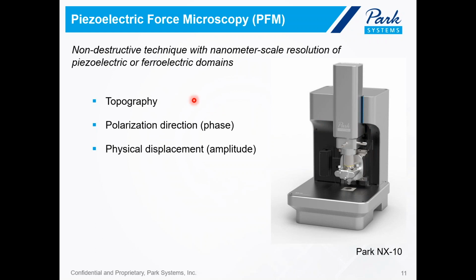So in PFM, we have 3 channels mainly. The topography channel is very self-explanatory. From the topography channel, what we can learn is the features at our surface, the topography, the morphology. And then we have a PFM phase and a PFM amplitude channel. From the PFM phase channel, we can get the polarization direction. And on the other hand, from the PFM amplitude channel, we can get the physical displacement. So that's about the channels we're looking at in a PFM experiment.